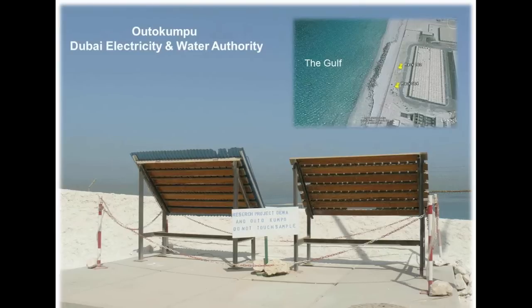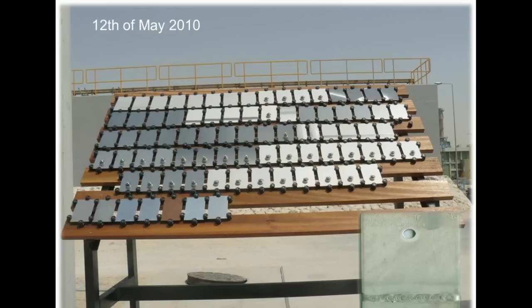Here's a picture from Google Earth showing where our 4 racks are located, and they are approximately 50 meters away from the Gulf. We are doing this research project together with Dubai Electricity and Water Authority. In total we have 4 racks where 2 are open and fully exposed and 2 are in a sheltered condition. So this is how the samples looked when we started the testing on the 12th of May 2010. You can see in the bottom right corner that on some samples we have also drilled a hole to form a so-called crevice, and on some we also have a weld to see what impact this has on the atmospheric corrosion resistance. The samples on the bottom row act as reference samples such as carbon steel, aluminium, zinc, and copper.